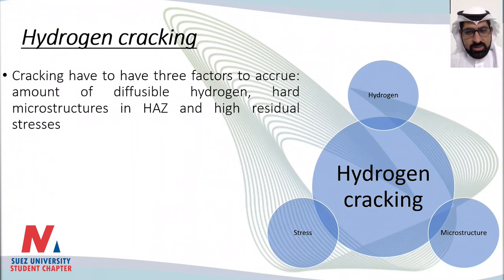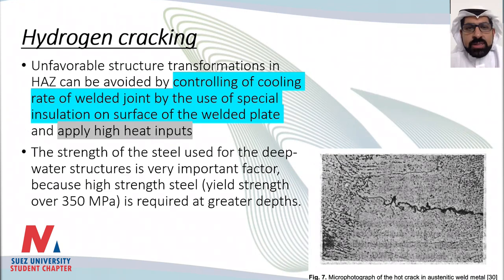Next slide, please. Unfavorable structure transformation in the heat affected zone can be avoided. How can we avoid that hard structure? By controlling the cooling rate of the welding joint, using special insulation on the surface of the weld plate, and also applying high heat input. And also choosing the right material. When you are welding in the deep sea, your yield strength has to be over 350 megapascals.